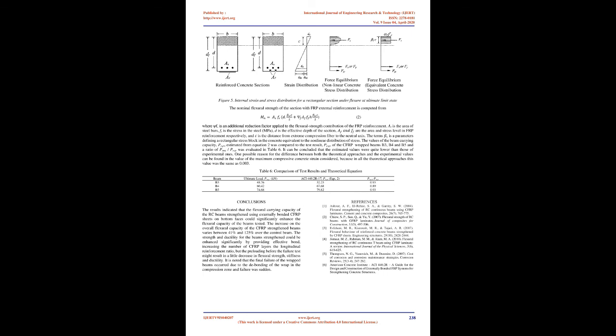Conclusions: The results indicated that the flexural carrying capacity of RC beams strengthened using externally bonded CFRP sheets on bottom faces could significantly enhance the flexural capacity of the beams tested. The increase in overall flexural capacity of the CFRP strengthened beams varied between 41% and 125% over the control beam. The strength and ductility of the strengthened beams could be enhanced significantly by providing effective bond, increasing the number of CFRP layers, and the longitudinal reinforcement ratio, but preloading before the failure test might result in a slight decrease in flexural strength, stiffness, and ductility.